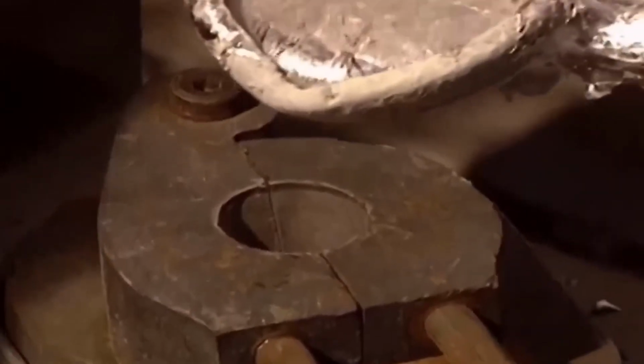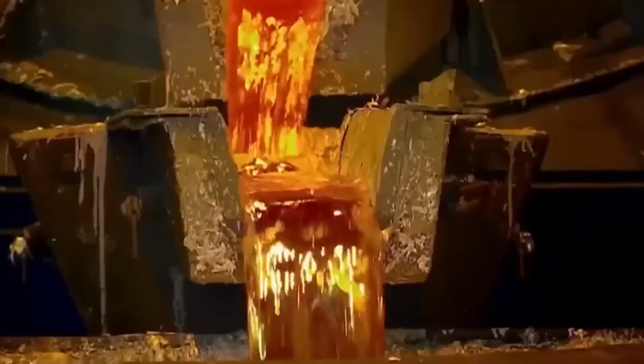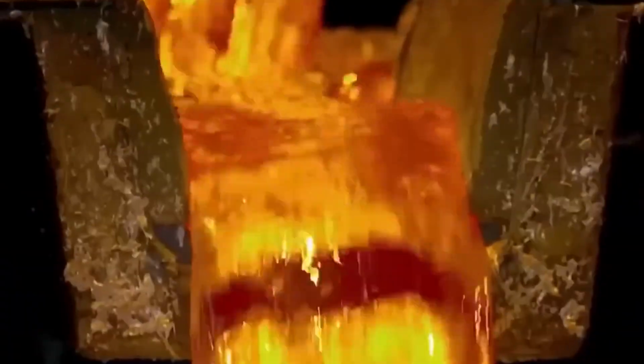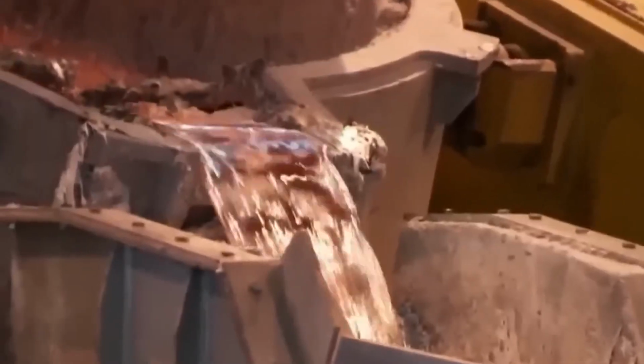Alumina crystals dissolve in molten cryolite inside the reduction pot to create an electrolyte solution that transfers electricity from the carbon rods to the pot's carbon-lined bed. A crust forms on top of the aluminum when an electric current is passed through the cryolite. A layer of pure molten aluminum forms on the bottom of the smelting cell when more alumina is periodically stirred into the mixture, breaking the crust and enabling the alumina to dissolve electrolytically.